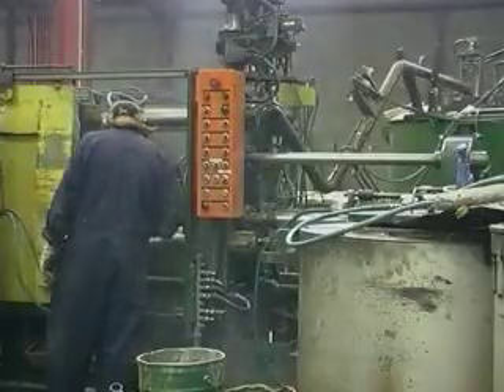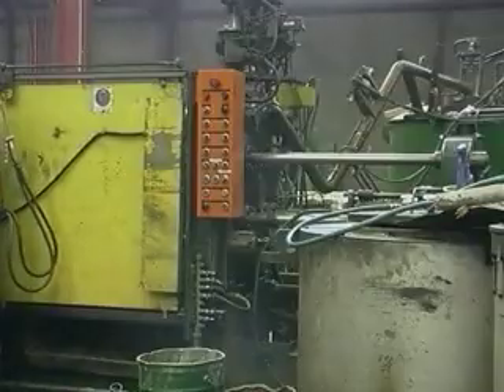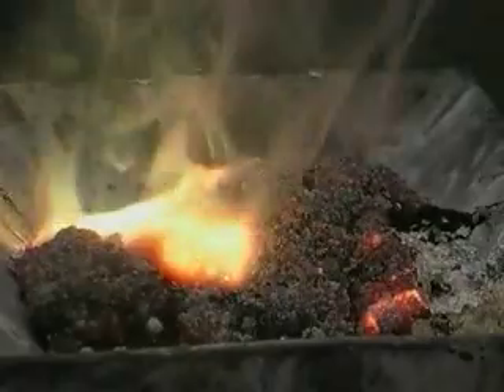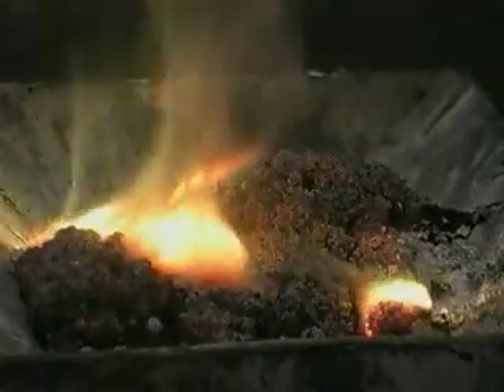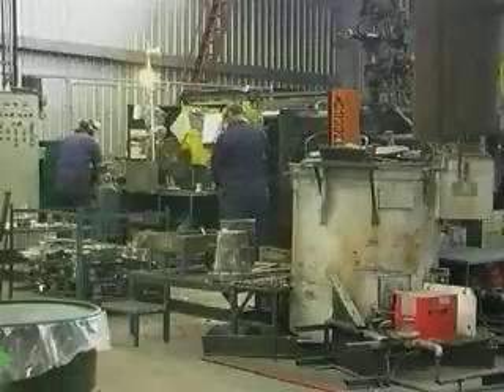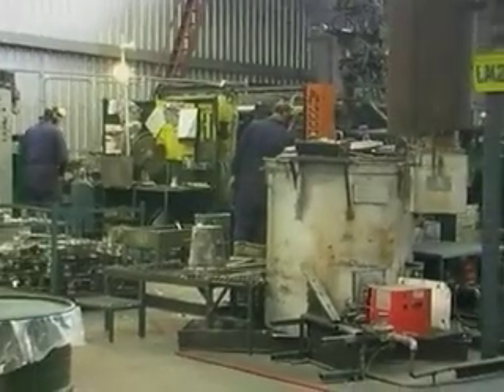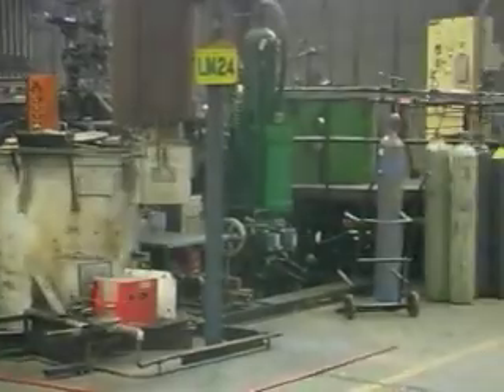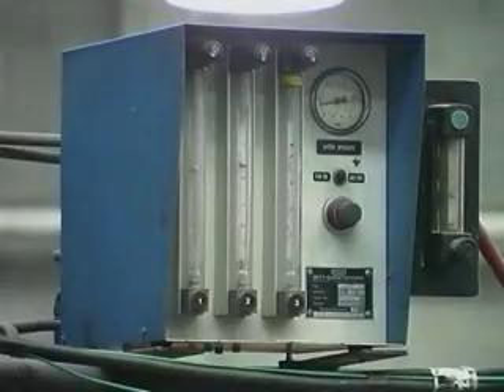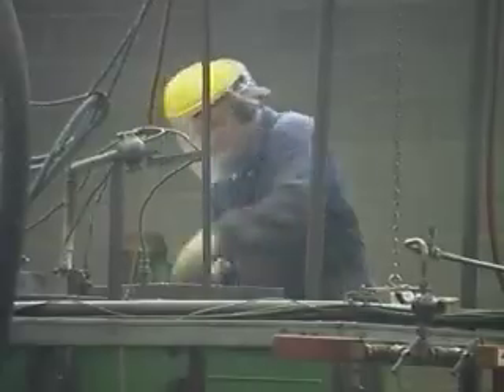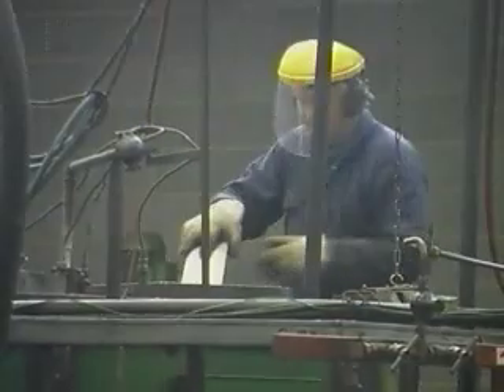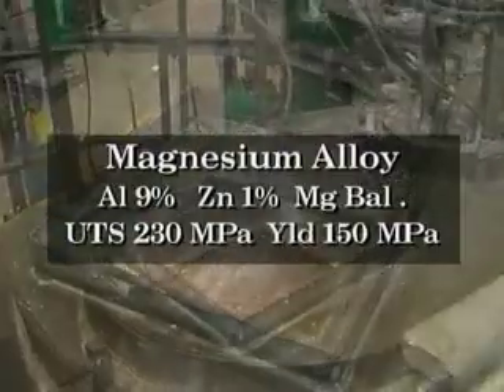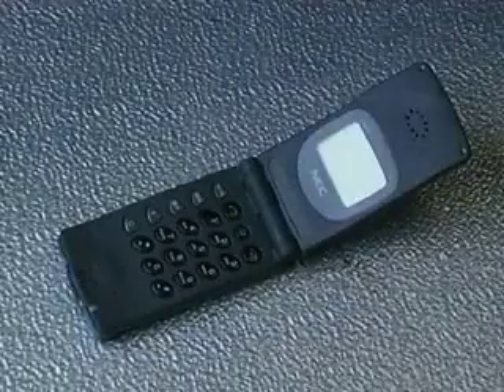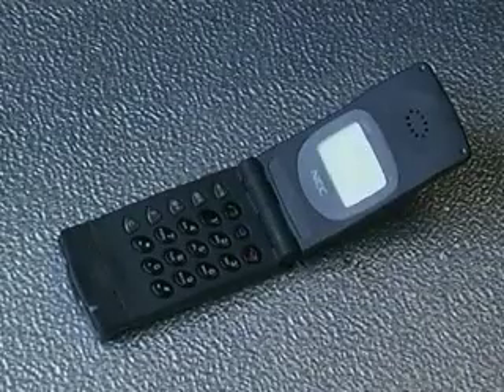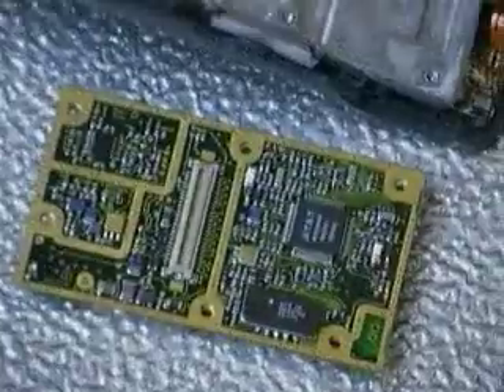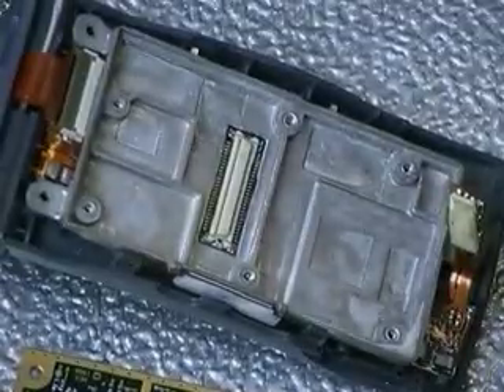Other materials used for high-pressure cold chamber die casting are the magnesium alloys and the brasses. Magnesium as small particles will burn in the air, so when used in conjunction with a high-pressure cold chamber die casting machine, it is necessary to use a mixture of gases that do not support combustion and are heavier than air to form a blanket which protects the molten metal in the furnace. The main advantages of the magnesium alloys are their high strength and stiffness to weight ratio. Mobile phones must be lightweight, strong and able to shield electromagnetic radiation. For these reasons, a magnesium alloy was selected as the material for their chassis.